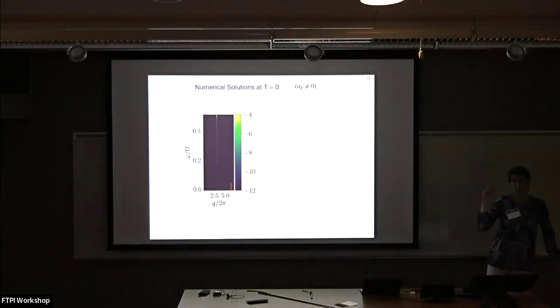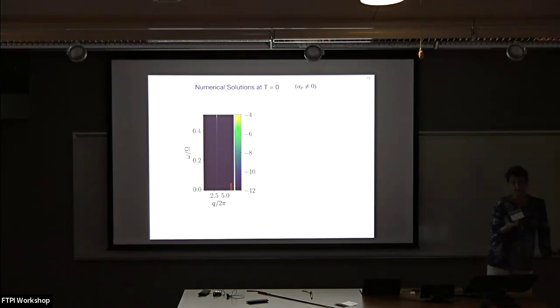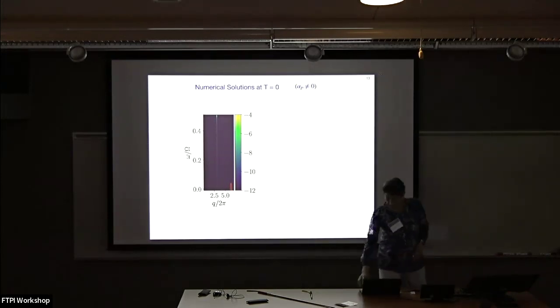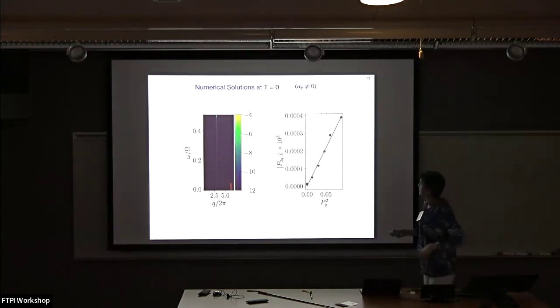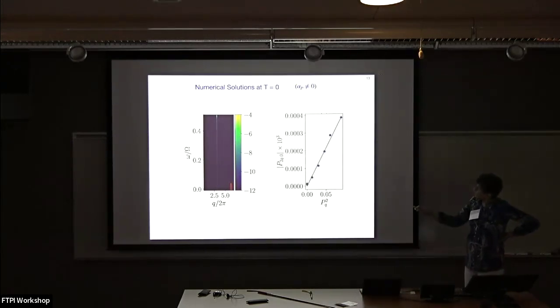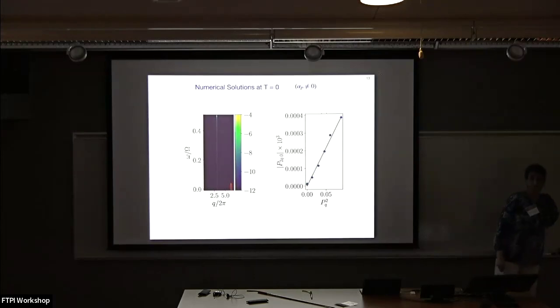Now, what happens when we put on our nonlinearity? This comes in as a P cubed term. So again, it only works in the system of parallel symmetry, like rhombohedral titanate. What happens then is, in addition to our parametric feature, we get a static feature at 2Q0. And what's interesting is it's significantly less in intensity, but if we look at that feature, it seems to scale linearly with our original parametric resonant mode squared. Okay, so that's what we have.